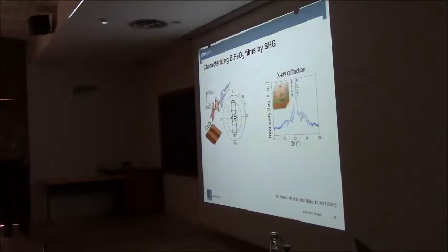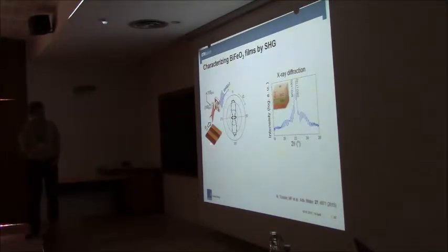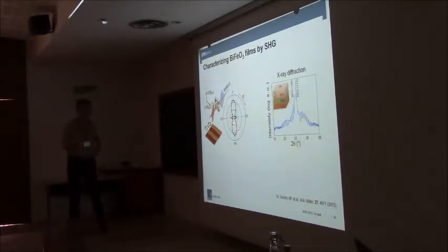Here, first of all, we see that a nicely grown bismuth ferrite film, bismuth ferrite, strontium ruthenate, dysprosium scandate, with a certain domain structure, in this case a striped domain pattern, gives a very specific second harmonic response. If you rotate the polarization of the ingoing fundamental light at omega, keep the outgoing second harmonic light constant, and rotate this ingoing polarization by 360 degrees, you get this shape.